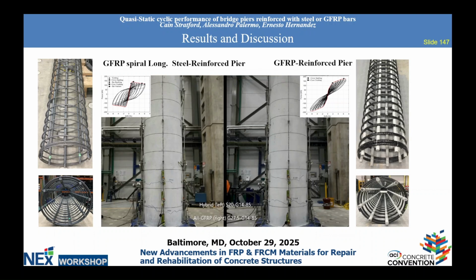Then we compare the benchmark with the full GFRP. Now, when we're looking at these, obviously, you will certainly say, oh, look at that. This is a terrible loop, hysteresis, because you have pretty much very minimal energy dissipation. So probably, if you look at the accumulated energy dissipation, I'll show you later, it is 30% of the benchmark. But there is an advantage, that is that the post-yield stiffness is ascending and not descending, and then you